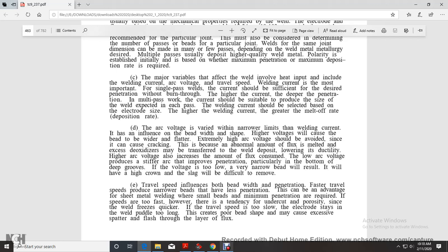Travel speed influences both bead width and penetration. Fast travel speed produces narrower beads and less penetration, which can be an advantage for sheet metal welding where minimum penetration is required. If the speed is too fast, however, there is a tendency toward undercut and porosity since the weld freezes quicker. If the travel speed is too slow, the electrode stays in the weld puddle too long, creating a poor bead shape and possibly excessive spatter or a flash layer of flux.